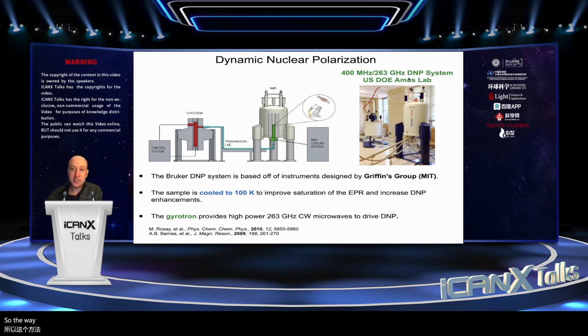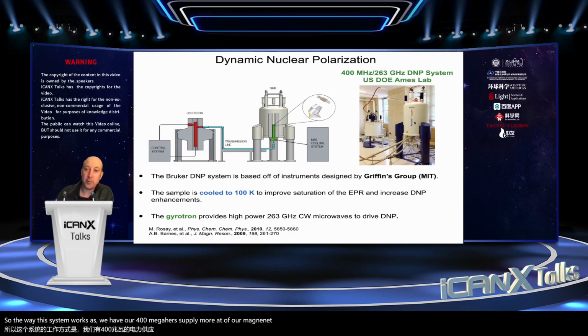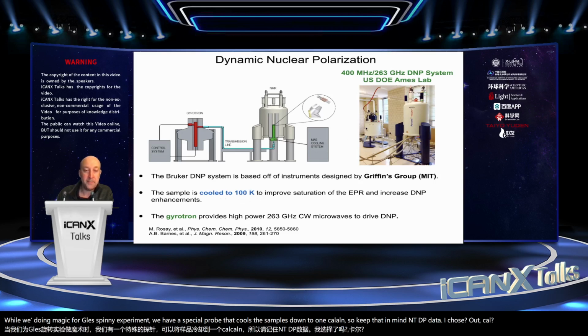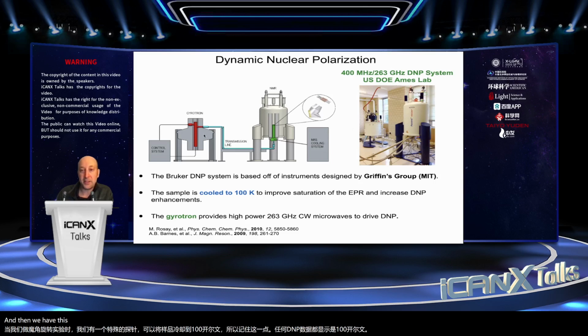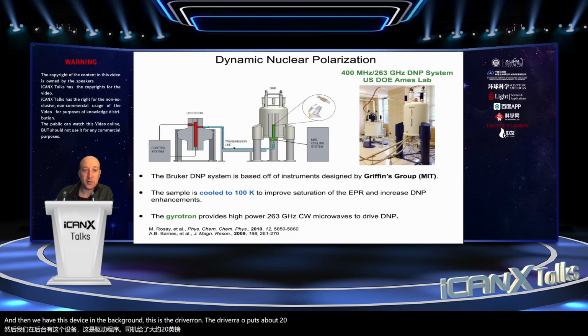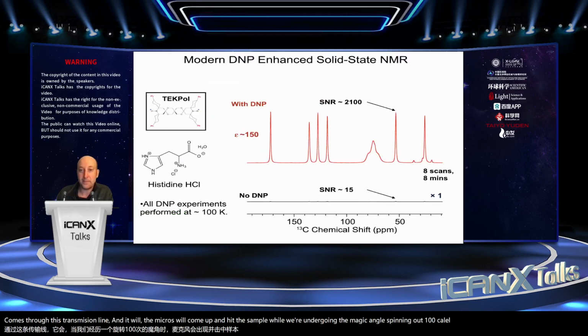So the way this system works is we have our 400 megahertz wide bore NMR magnet. This is where we're going to do the NMR experiments. While we're doing a magic angle spinning experiment, we have a special probe that cools the samples down to 100 Kelvin. So keep that in mind. Any DNP data I show is at 100 Kelvin. And then we have this device in the background. This is the gyrotron. The gyrotron outputs about 20 watts of 263 gigahertz microwaves, which come through this transmission line and hit the sample while we're undergoing the magic angle spinning at 100 Kelvin.